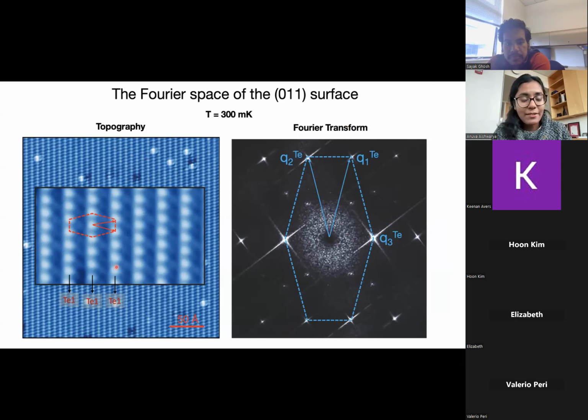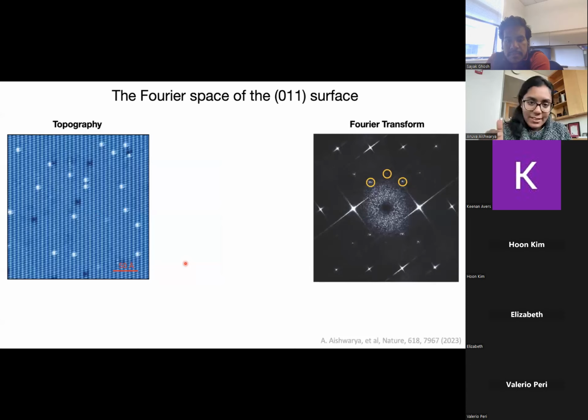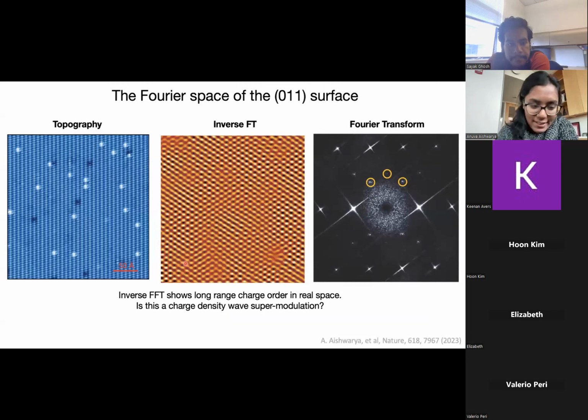However, apart from these lattice Bragg peaks, we see additional modulations which are at smaller Qs, which means they're larger in real space. We can also see that they're at the vertices of the Brillouin zone. If we pick up this Q vector and do an inverse Fourier filtering, we can actually visualize these modulations in real space, and it's pretty long range ordered.